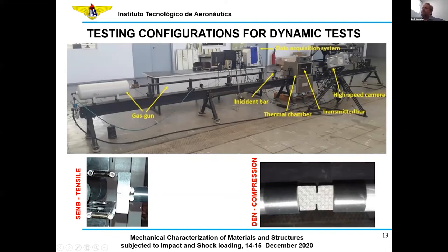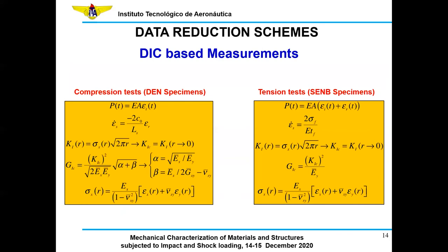The two pictures in the bottom here show the details of the specimens placed in the split Hopkinson pressure bar. Again, they were white painted to aid the visualization and also to improve the contrast during the DIC measurements. And by using the dynamic equilibrium, we can actually show that for the DEN specimen, the forces at the bar ends can be computed from the transmitted pulses.